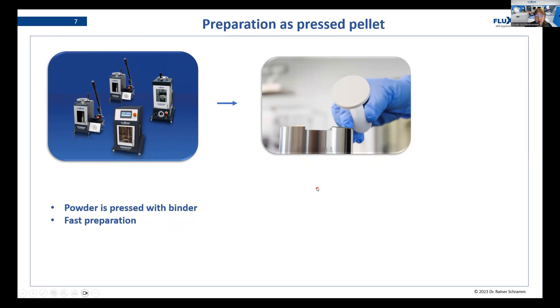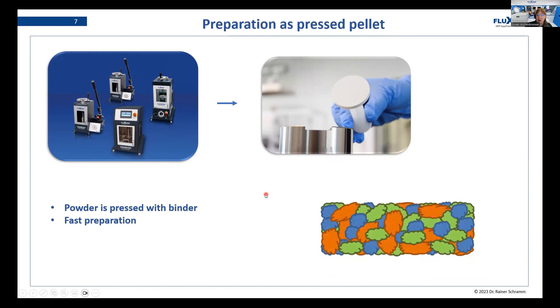Why is this better than just preparing a loose powder? If you prepare a loose powder in a cup, you cannot use vacuum for your measurement and you will have a lot of air in between particles. As soon as you have a pressed pellet, it's also easier for handling the sample, and your sample will be compressed so that there's no air in between particles, which leads to better representation.